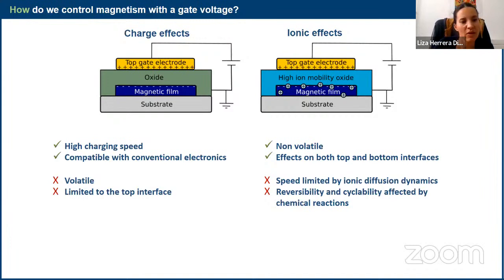This type of device has the advantages of high charging speed because it's electronic, and it is also more compatible with conventional electronics. However, if we want applications where we need non-volatility of this gated state, then this is not the way to go, because this is volatile. It's a charge accumulation. We switch off the gate voltage and the effect goes away. And this is also limited to the top interface, where we accumulate charges.